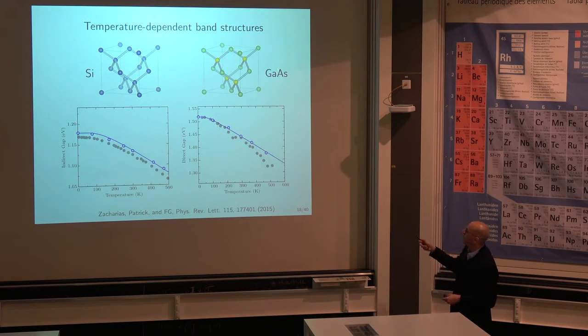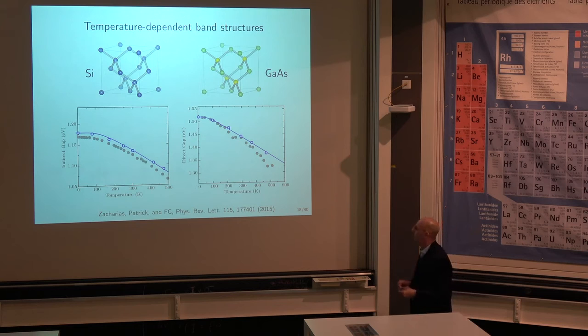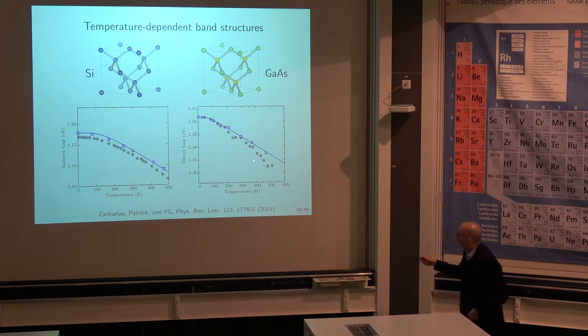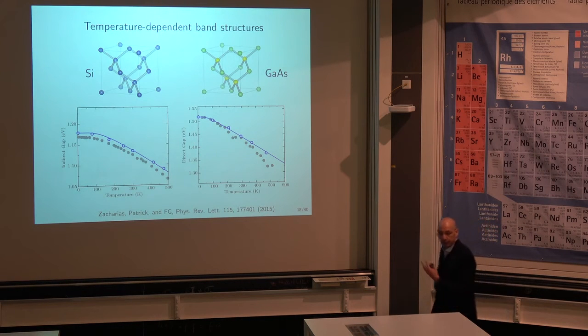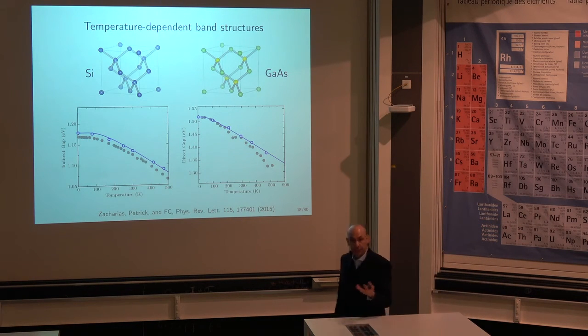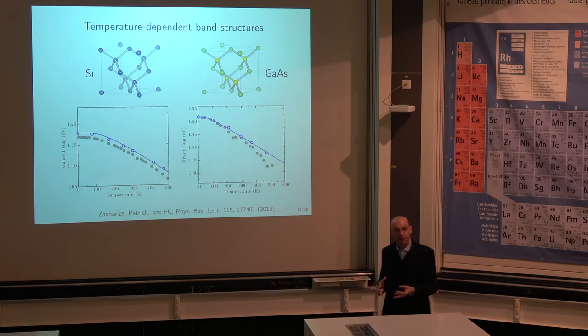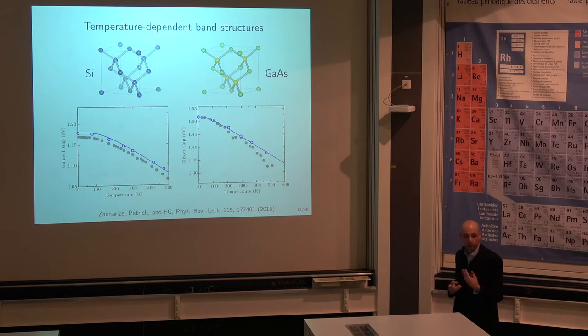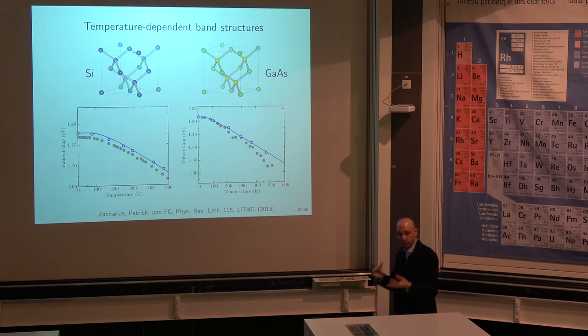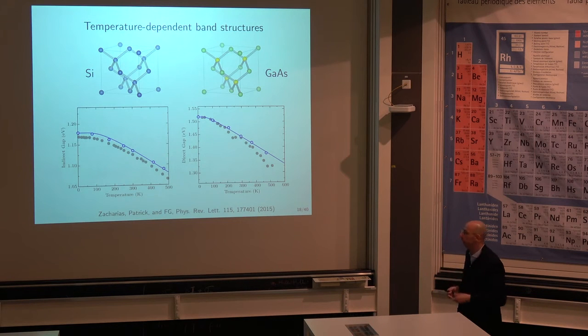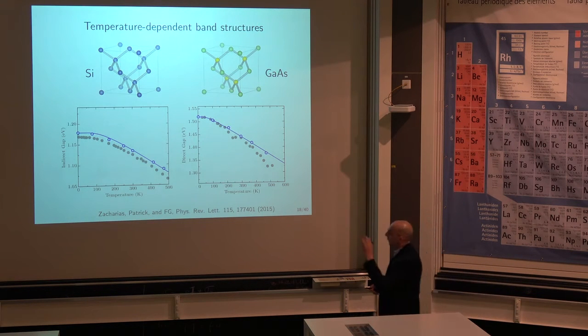That's a similar situation, but for gallium arsenide, it's a similar material. In this case, it is a polar material. And what you will notice actually is that the calculations start deviating a little bit from experiment at high temperature. There is a reason for this. We are doing a theory in the harmonic approximation. It turns out that gallium arsenide has a larger lattice expansion than silicon when you go to this kind of temperature, and these effects cannot be ignored, okay? So if you incorporate nonlinear, so basically anharmonic terms in the form of lattice expansion, you would recover basically this line. So that's another kind of subtlety one may take into account. So these are band gaps. So what about band structures?